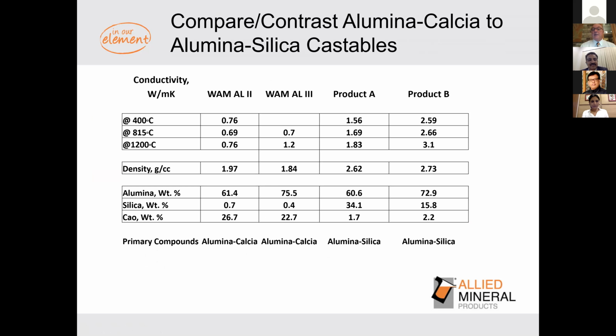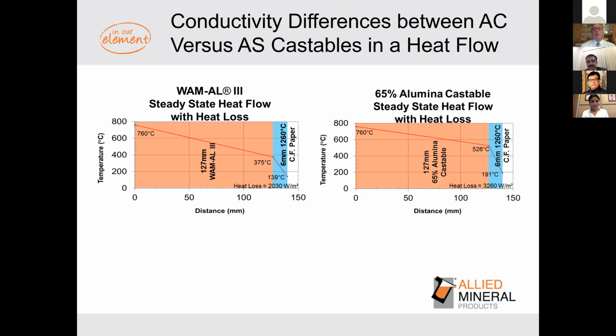Okay, the other advantage of this calcia-based material is the thermal conductivity. You can see here these are two calcia-based, and these are more typical refractories, and you can see that it's less than half of the conductivity. So that difference in conductivity will translate into lower temperatures of your shell. With the calcium-based materials, you have 139 degrees C versus 191. I know in a lot of parts of the world, energy is a very large cost, so lower heat loss is a fuel savings.